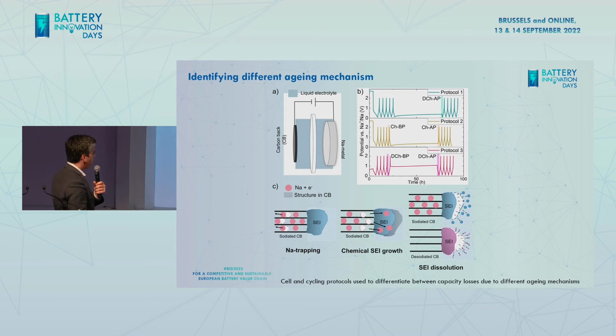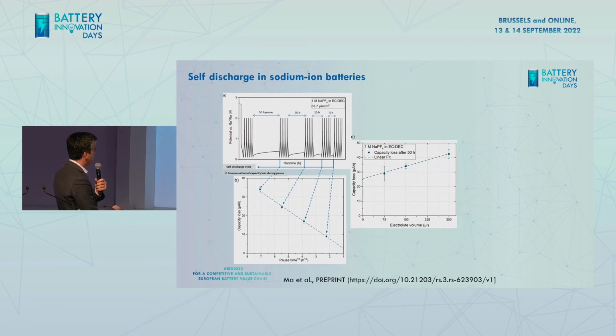And just to highlight the importance of this, if you look at the y-axis on the left, capacity loss, you can see that it is reported in microamp hour. So you can think about it, how small such a current and such a capacity loss is. This is almost 1/10 to 1/20 of the total capacity. So it's very, very small loss that is very difficult to quantify.